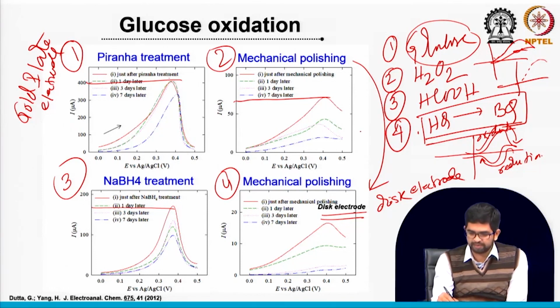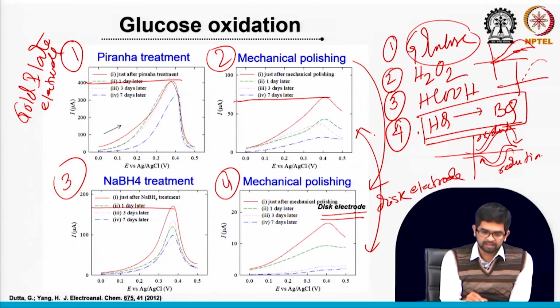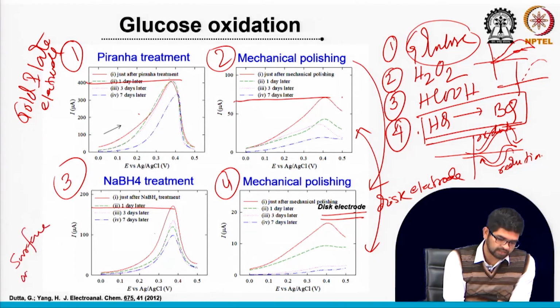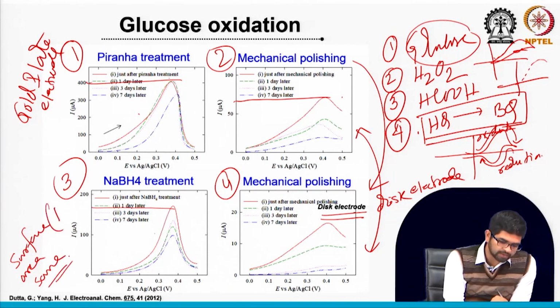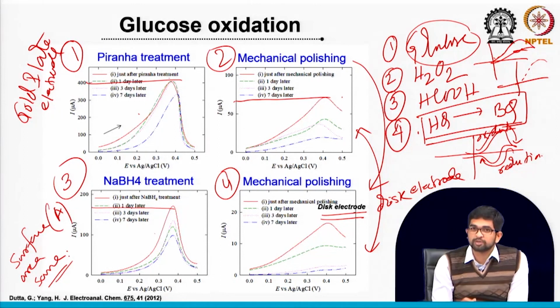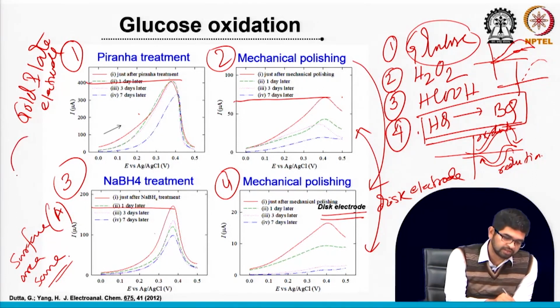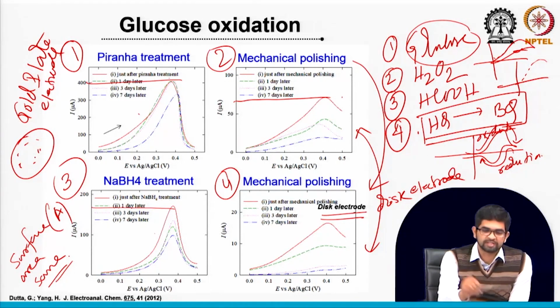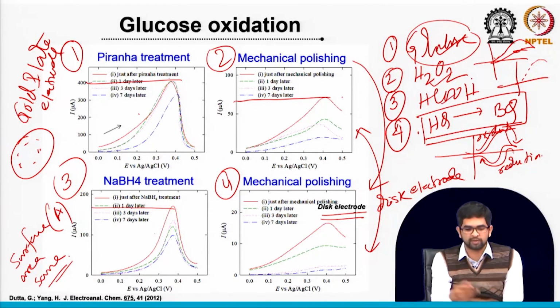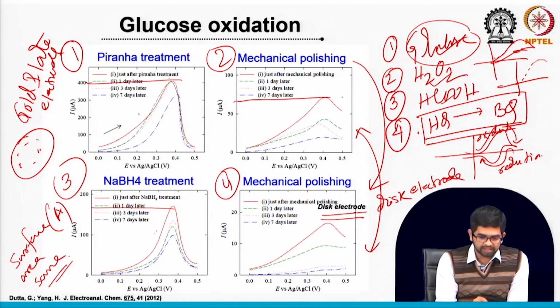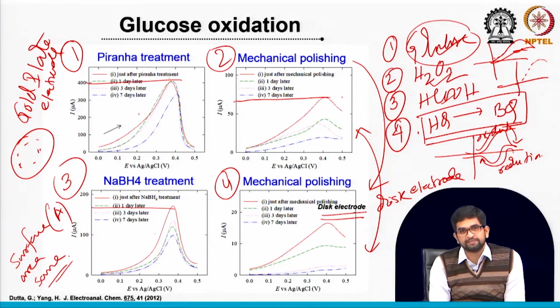For the disc electrode case, definitely the disc electrode and the plate electrode have different surface areas, so you cannot compare this and this. But in 1, 2, 3, all three cases, the surface area is the same. Why am I saying the surface area? Because the current is directly proportional to your electrode surface area. If you have a higher surface area, you will get more active surface for oxidation of your substrate, like glucose, hydrogen peroxide, formic acid, and definitely a higher current. So in these 1, 2, 3 cases, you still see the piranha case giving the higher current, though the surface area is the same. This is because piranha can enhance the activity much better than the other treatments.